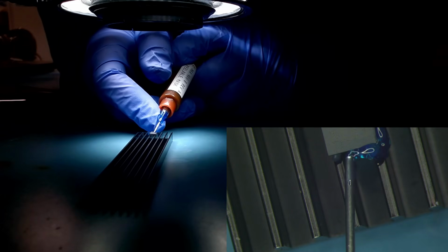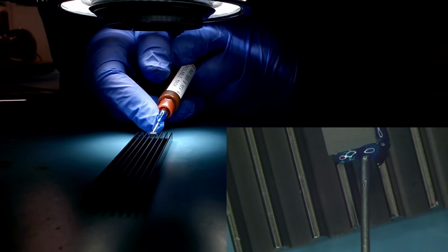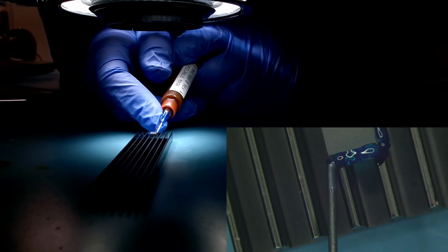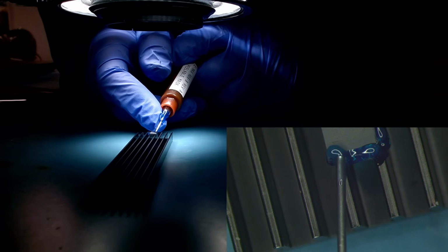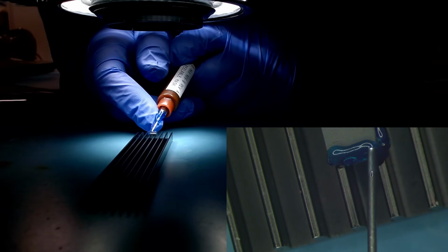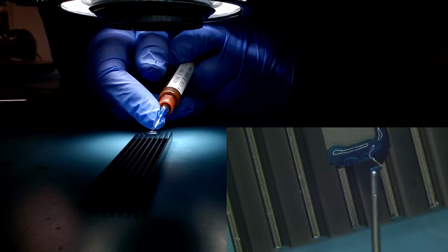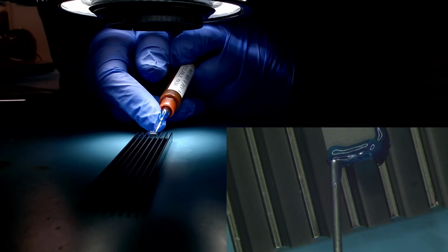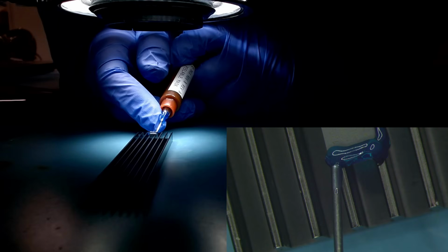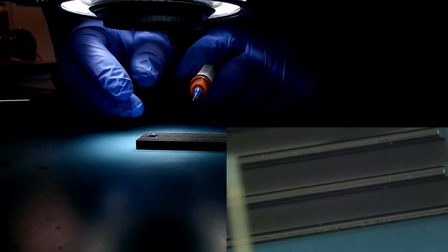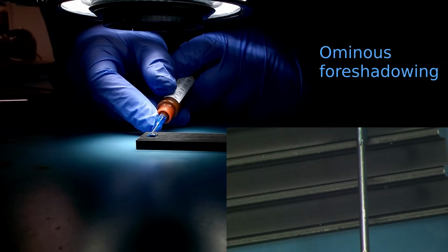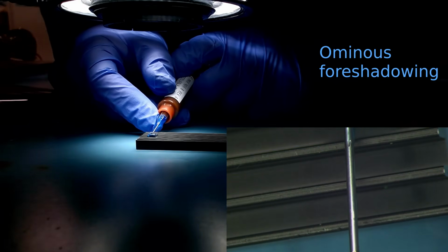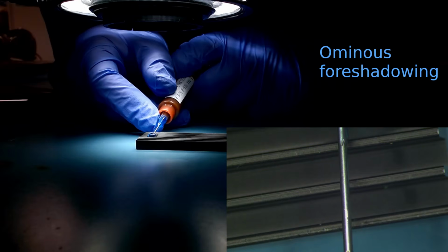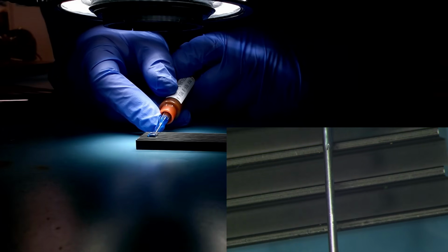Make sure you get good coverage. This is the first time that I've tried using this particular heatsink. I've used a flat surface in the past and I've had some issues with it as far as delamination and so on. My hope is that any acid overspray and so on with the heatsink will just fall down into the channels and fall away from the device. And so we're not going to have to worry too much about corrosion on the underside. I'll probably see if I can get a little bit of the mask on the underside just to be safe, but I don't think it's going to be necessary.